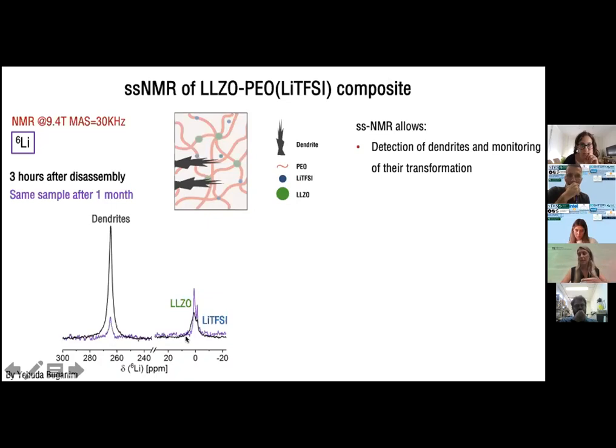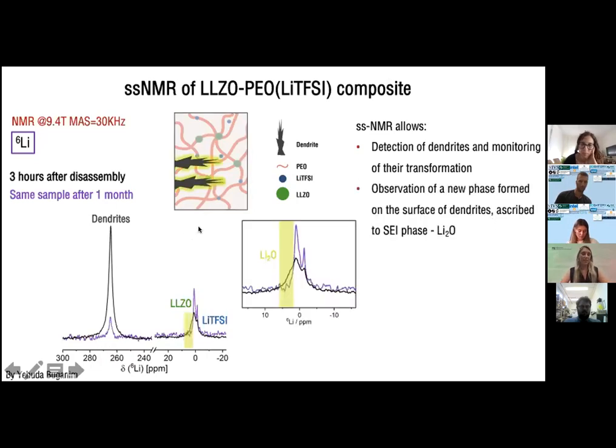significantly. So we can say that solid state NMR allows us to detect and monitor the dendrites and their modification, transformation, and degradation. And as I told you, we also have the SEI that covers them. So can we see that? Yes, we can. We observe a new phase whose formation and disappearance is correlated to the formation and degradation of the dendrites. So we can deduce that it probably grows on the dendrite. And from the chemical shift, we know that it's lithium oxide.